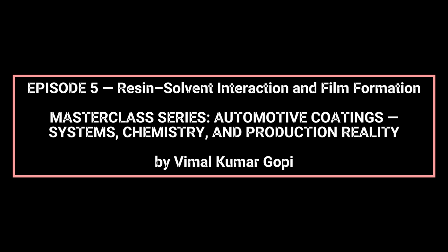The cause-effect relationship between resin-solvent compatibility, evaporation, and rheology is direct. A mismatch in solubility parameters can lead to early skin formation or uneven flow. Incorrect solvent ratios may produce gradients in viscosity across the wet film, resulting in orange peel, sag, mottling, or solvent popping. Conversely, optimized resin-solvent systems deliver smooth, continuous films with uniform appearance and minimal defect sensitivity.